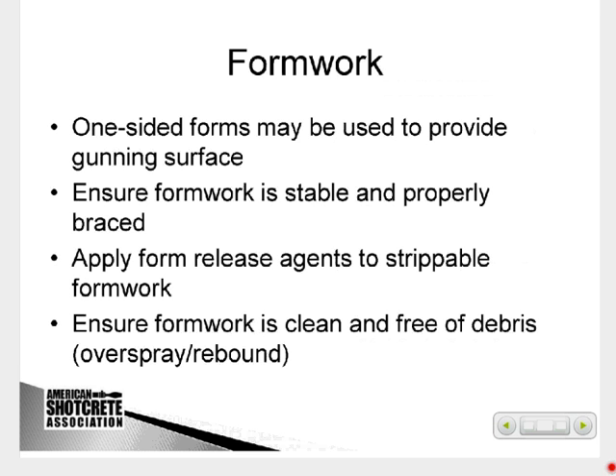I mentioned before, we typically use one-sided forms. The form needs to be stable, so if you're shooting against it, it's not going to vibrate and create issues with cracking of the fresh shotcrete before it's set. You can use form release agents just like in cast-in-place work to allow stripping of the formwork. There are many applications where the formwork just stays in place. I showed you that basement wall where it was steel piles with lighting in between and it's basically shot in place and left there.